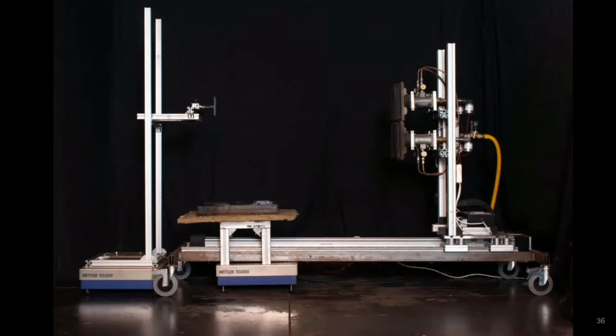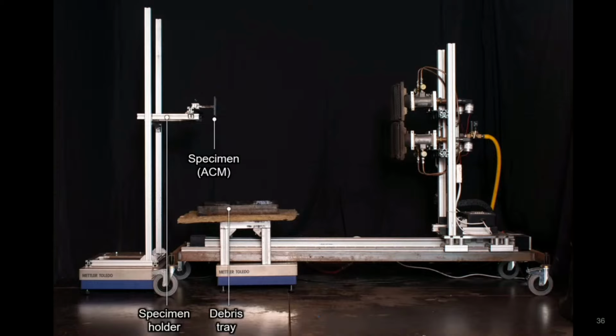Experimental specimens were mounted onto a specimen holder, as shown here, and were held above a tray which was used to catch any falling debris. Both the specimen holder and the debris tray were placed on balances, essentially digital scales. And these were placed there to measure the masses lost by the product or mass gained by the debris tray throughout the experiment.